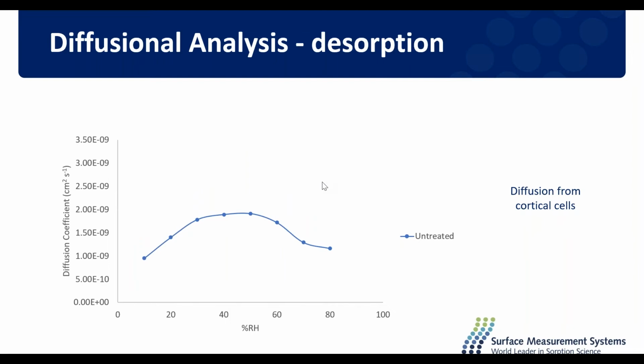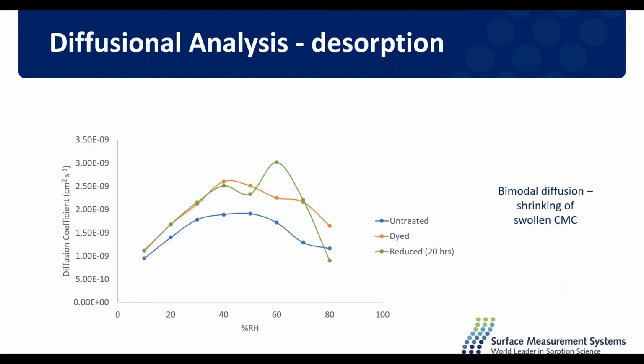Now, here are the diffusion coefficients for untreated hair during the desorption isotherm. And this has quite a simple one peak, and that has been related to the diffusion from the cortical cells out of the hair fibre. If we look now at the dyed and reduced samples, we see a more bimodal shape appearing. We can see that it's much faster.